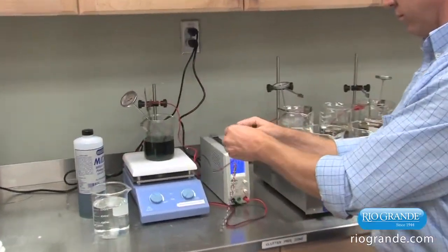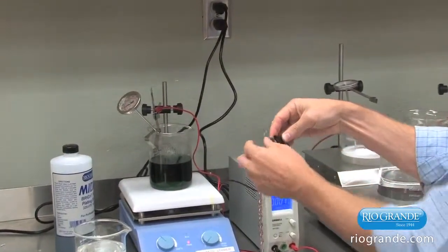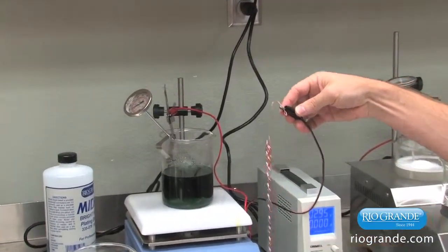When plating rhodium on bronze, brass, copper, or pewter, a nickel preplate must first be added to prevent contaminating the rhodium solution.